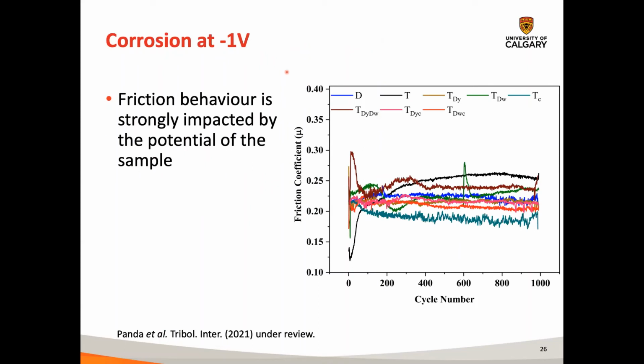And so what we see is when we apply this -1 volt to the sample, we really change the friction coefficient. So if you remember, the TDS water really increased the friction coefficient a lot higher, and these values are very similar to what they were before for the other additives. And so the corrosion is really impacting